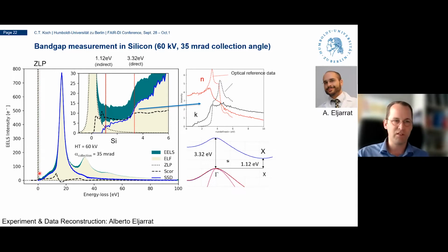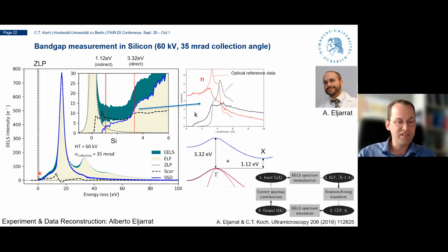So he then developed this reconstruction algorithm. This is also something that is computationally quite demanding and runs on GPUs and takes a while to process multiple spectra. But it basically tries to self-consistently reconstruct the dielectric function of this material, taking into account the thickness of the material, the primary beam energy, and relativistic effects that produce artifacts in these spectra, to then retrieve the dielectric function. So this is the dielectric function represented in n and k. These dashed lines here are from the database. I have a link to that in the next slide. I forget the name. It's a dielectric function database. So this is from optical measurements, the reference data. It doesn't quite look like the reconstruction that we obtained from these experiments, despite this advanced reconstruction algorithm here.